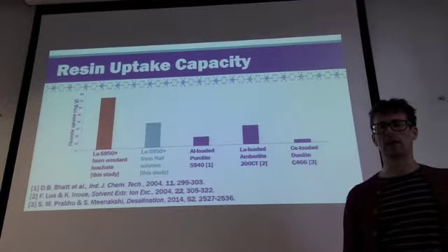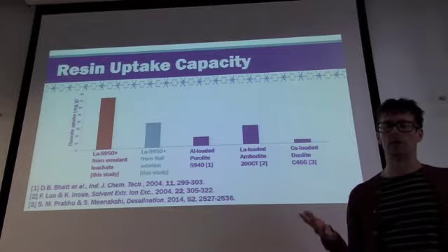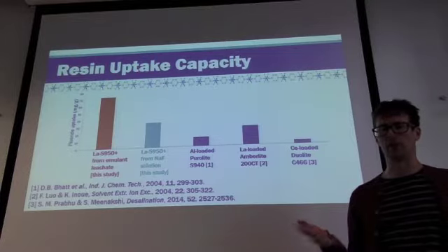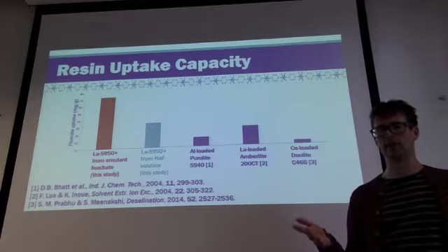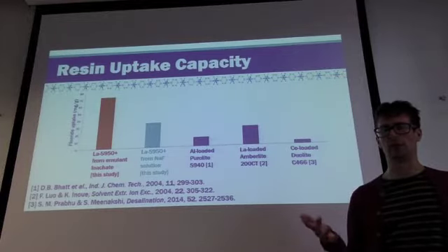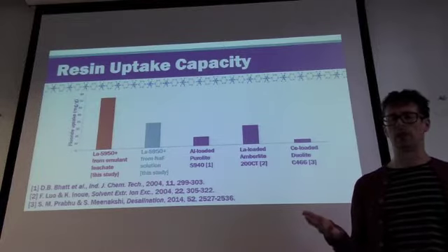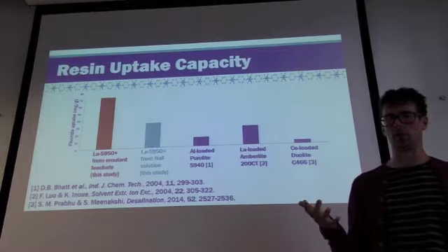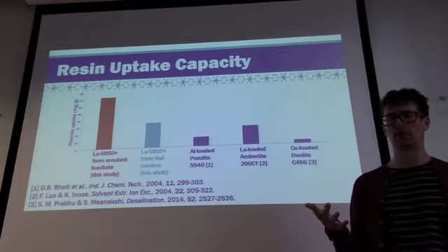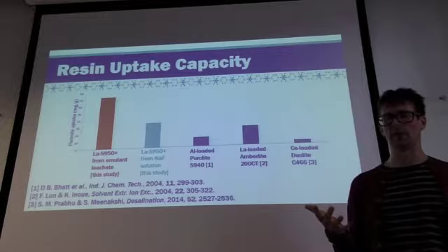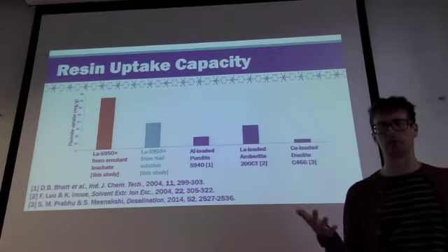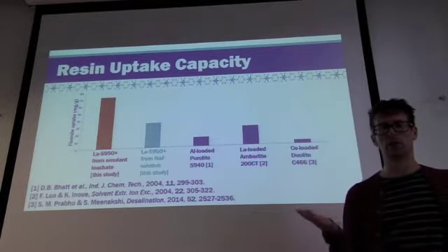This is actually highly unusual behaviour because when previous researchers have added other anions and cations to the system, it's either had a negligible effect on the fluoride uptake, or it's actually decreased it because of other anions in the system competing with the fluoride for binding sites on the metal. What you'll never see is an enhancement effect, but that's precisely what we have here. So why should this be?